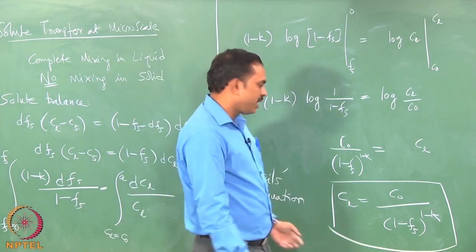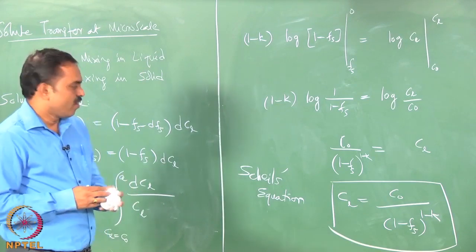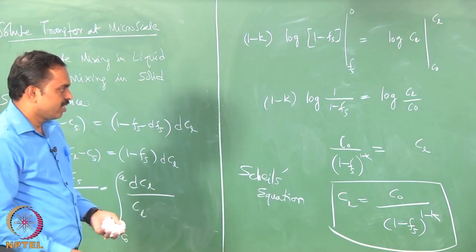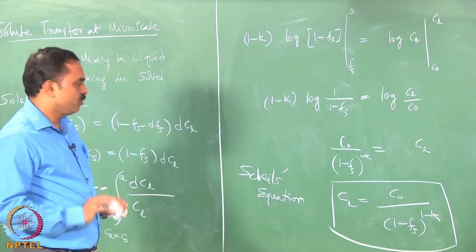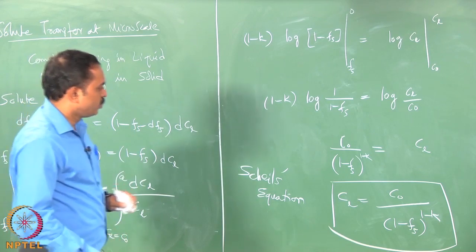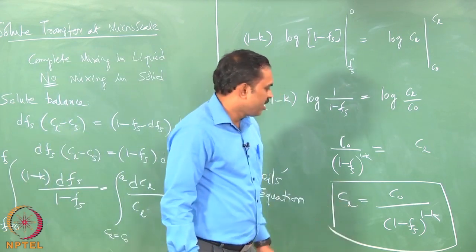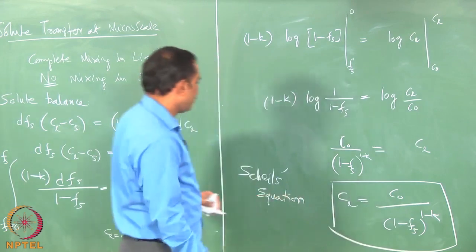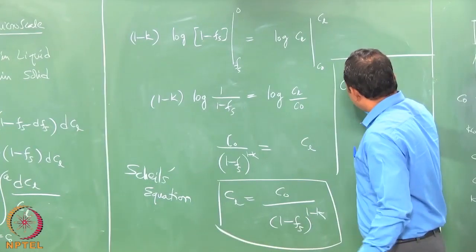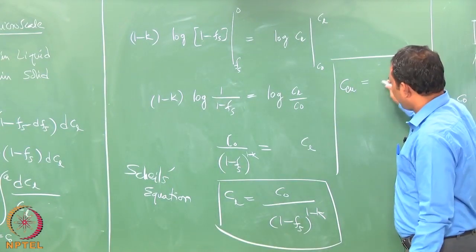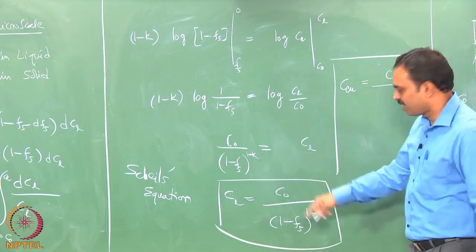Okay. And we can apply Scheil's equation to derive the eutectic fraction towards the end of the solidification, even though you are not expecting eutectic to form for the alloy composition that you have chosen. The way you do it is just substitute for CL the eutectic composition, and find out what the FL would be. So we could do that very simply here. I would just illustrate here. If C eutectic was known, then you have C naught, and what was supposed to be found out is the eutectic fraction, which is the liquid fraction.